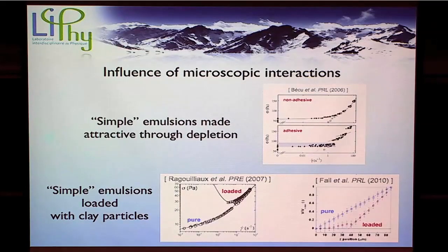These are experiments. This is another motivation to look at these questions, where you see that within the same systems, when you change, for example, emulsions and you make them attractive through depletion, you will have, in the non-adhesive case, the typical Herschel-Bulkley curve, whereas in the adhesive case, you will have this plateau. This is difficult to distinguish, I agree. So what you really need to do to distinguish this type of dynamics is to look at spatial flow. And you see that, for example, in this emulsion experiment, they have here the shear band that appears.